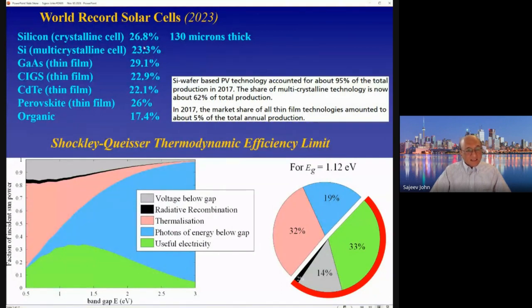And this stagnation in the rise in efficiency has led to the study of a large variety of other thin film solar cells. Gallium arsenide is one of the most prominent. It has the highest efficiency of any single junction cell with 29.1% efficiency. Another one is this copper indium gallium selenide thin film, which has an efficiency close to 23. Cadmium telluride, which also has already found a number of commercial applications, is slightly below that. There's been a lot of interest and excitement in perovskites, which are very inexpensive to make.